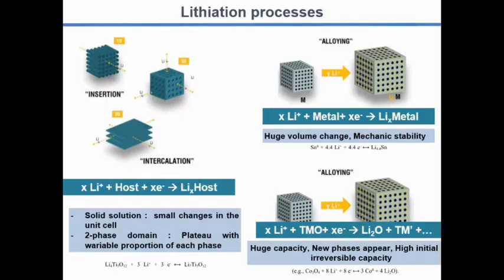We have, in fact, three mechanisms when lithium is moving from one side to the other side, when ionic lithium is going into some solid electrode material on the anode side or cathode side. The first mechanism is intercalation or insertion. So lithium is inserted in the host matrix, which has a one-dimensional, two-dimensional, or three-dimensional structure, and lithium is forming only a weak bond, so it's very easy to insert and to extract lithium during the charge and discharge process. This is the more reversible phenomenon during cycling of the battery.